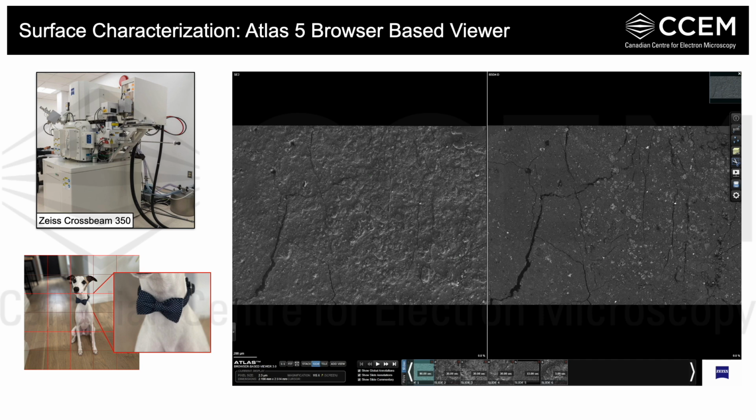Here on the right, we are looking at the surface of a meteorite that we've mapped in the SEM using both secondary electron, which is shown on the left, and backscatter, which is shown on the right. As you can see by the scale bar, this is a pretty big area. The field of view is around 2 millimeters by 1.5 millimeters. So if we wanted to image any of the small features here, we'd have to zoom in to specific areas, focus, take our image, and then repeat this process over and over again.